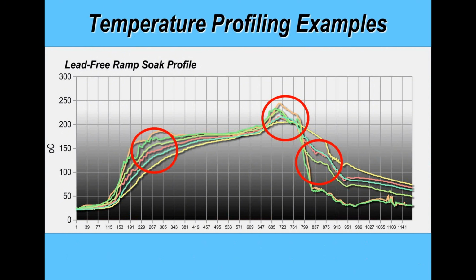On certain components like LEDs, light emitting diodes, it can affect the performance of the part. It obviously affects the solderability or wettability of the basic board. If you're running nickel gold or solder coated boards, it probably doesn't have very much impact. But if you're running tin and copper OSP, it has a dramatic impact, particularly if you're going to do double-sided reflow and then selective soldering, or any selective or wave soldering operation on through-hole parts after your initial reflow.